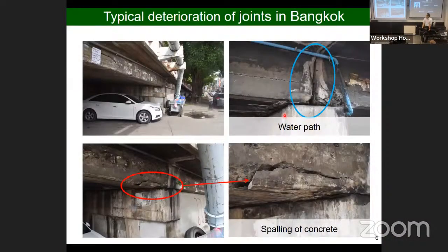Then another issue is water. In the case of Thailand, there is much heavy raining, sudden rain, and especially at the side of the beams there are some gaps, and strong rain leaks in here. Then there is spalling and corrosion. Corrosion can be induced by water penetration and also oxygen. That kind of deterioration is often found at the side of beams.